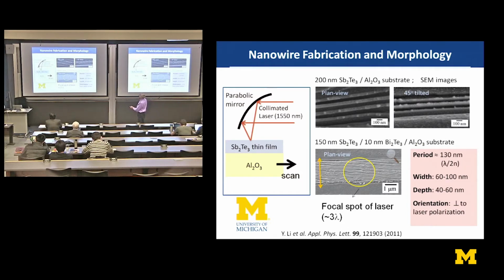We saw very, very narrow wires of widths a little bit less than 60 nanometers, actually, and with a period of only 130 nanometers. And remember the scale here. This is 1 micron. So how come something is forming here with a scale that's much smaller than the optical diffraction limit of the laser spot?